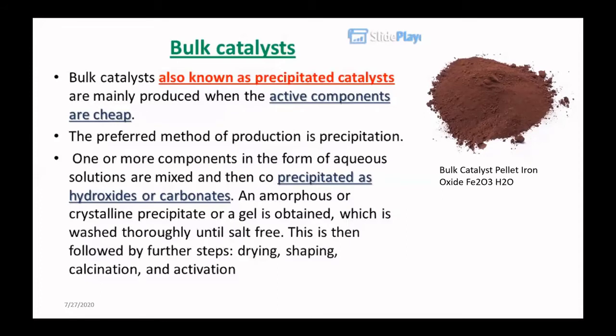Sometimes bulk catalyst, also known as precipitated catalyst, is produced when the active component is cheap. The preferred method of production is precipitation, where one or more components in the form of an aqueous solution are mixed and then precipitated as hydroxide or carbonates. But it agglomerates easily. The sintering process can agglomerate these materials because the particles can join together because of the heat treatment.